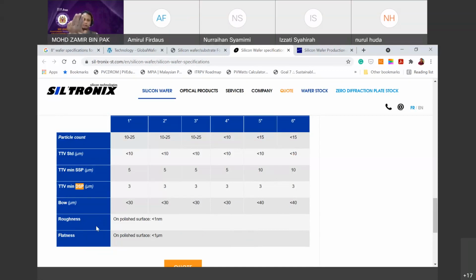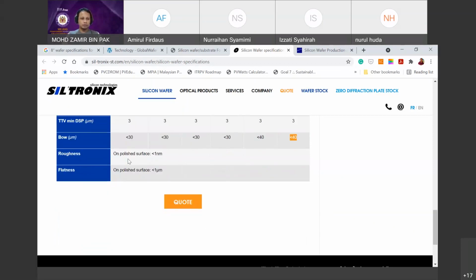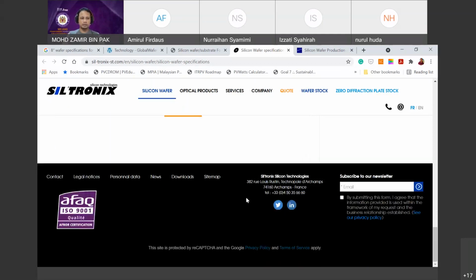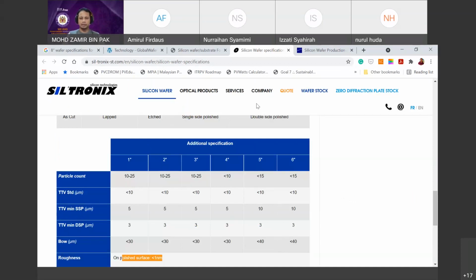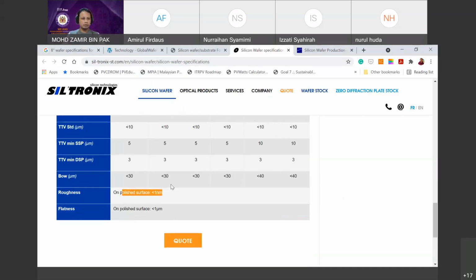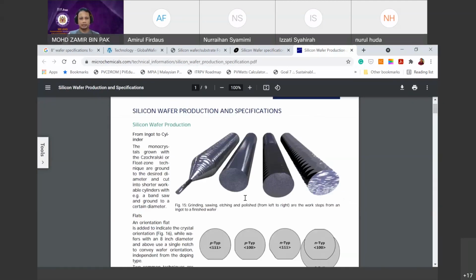So you can nampak dua-dua shiny. So bowing less than 40 micron means bowing ni means wafer tu dia bow how much? Dia bengkok, dia bengkok. So you don't get to see that the naked eyes, but then if you do some measurement, it can tell you how much bow do you have, right? So surface roughness for a polished surface is controlled below 1 nanometer. So that means a very, very smooth surface. So yeah, this is among the example that you have on the wafer spec. And then let's have a look at another one.